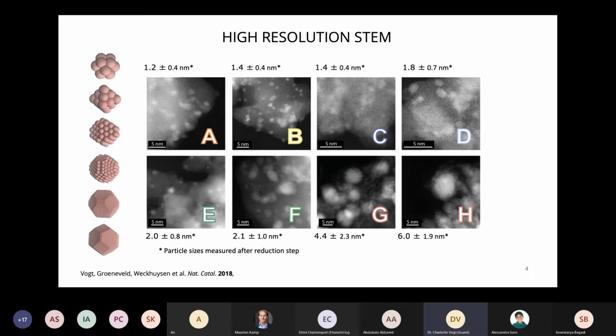And we extensively studied these types of reactions over the last couple of years. And we used a set of silica-supported nickel nanoparticles. These were created by deposition precipitation in a range of about 1 nanometer to about 6 nanometers. And this was quite an effort to synthesize these. Especially for transition metals, it can be quite difficult to synthesize, especially small nanoparticle sizes. So we were very happy that we were able to obtain that. We fully characterized those, of course, with all kinds of different laboratory techniques, high resolution STEM, hydrogen chemisorption, etc., to make sure that really the only thing changing in that set of samples was the particle size.